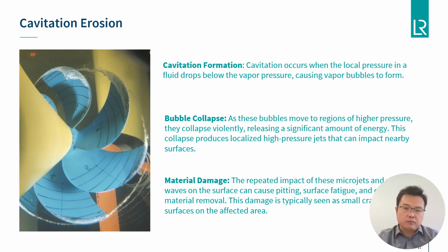Usually during the interaction between the propeller blades and seawater, cavitation can occur when the localized pressure in the fluid drops below the vapor pressure, causing vapor bubbles to form. After these bubbles form, they move to regions of higher pressure and then collapse violently, releasing a significant amount of energy. The collapse produces very localized high-pressure jets that can impact nearby propeller surfaces. Eventually, the repeated impact of these microjets will cause vast damage to the propeller material, causing pitting, surface fatiguing, and ultimately material removal, which is very similar to what we are observing now.